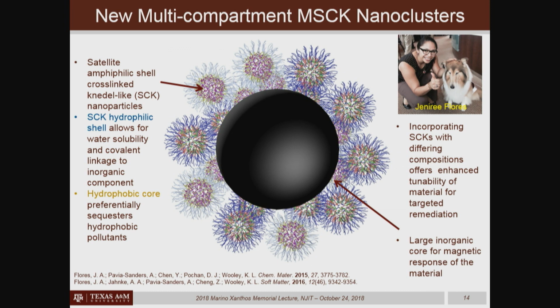Okay, so then let me turn to the second morphology for these materials, and that's the work of Jenny Flores. And Jenny was interested in being able to access the cleanup of pollutants in an environment where there might be complex mixtures of pollutants. And that's why we came up with this kind of a design strategy, where Jenny said, well, maybe one of these particles should be optimized to take up crude oil, and maybe another one should be optimized to take up perfluorooctanoic acid, and maybe a third would pick up arsenic or mercury or something. So we could have individual organic particles optimized for particular pollutants, and then bring them together into a composite structure where there would be a central magnetic nanoparticle onto which these were connected.